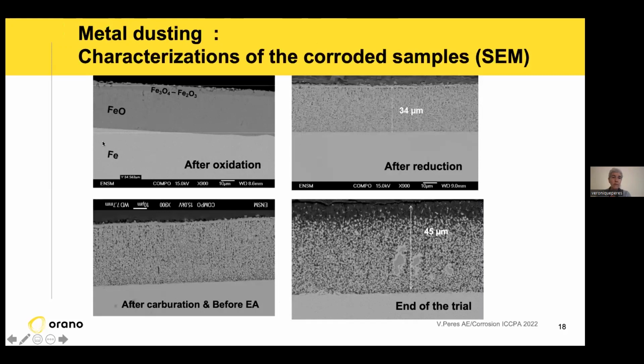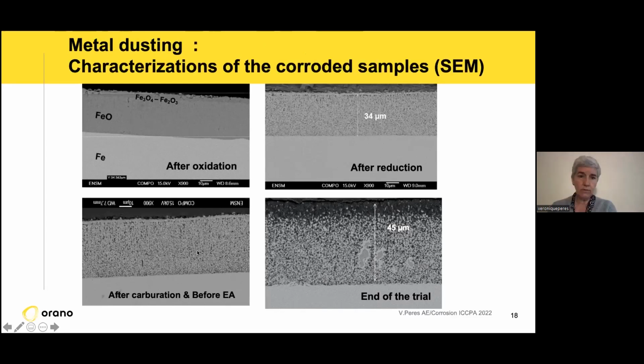If I can show you some pictures of the sample we have, this is iron, with iron oxide on the top surface and more iron oxides in the center. After reduction, you have the reduction of this internal layer of iron oxide. After carburation, you can see, just before we can have acoustic emissions, the beginning of the increase of carbon inside the layer, and after that you begin to see here a clear view of what happened with COx. And so what we can see here is that all these steps are without any acoustic emission. They are not so dangerous, and beginning with the real metal dusting process, you have some noise, so it can be recorded by these systems.